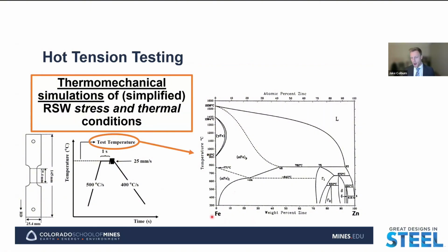Here we have our iron-zinc binary phase diagram, or the zinc-rich corner of the phase diagram. We see that in our general test temperatures for hot tension testing, around 600 to 900 degrees Celsius, we have a range of different iron-zinc intermetallics, as well as the phase fraction of those intermetallics and the liquid phase present, depending upon what test temperature we're at, how much diffusion has occurred from the coating, and how much zinc and iron is present at that point.